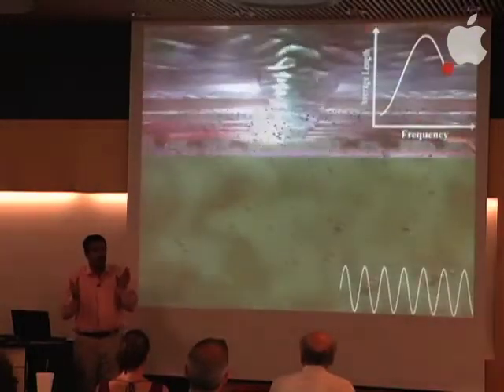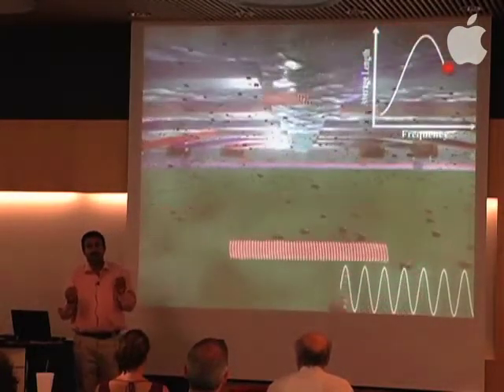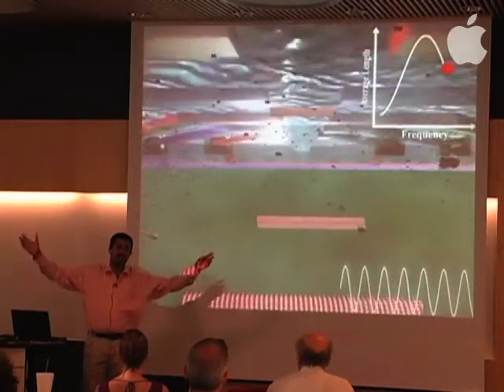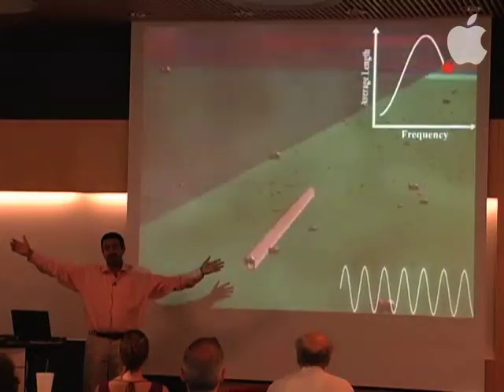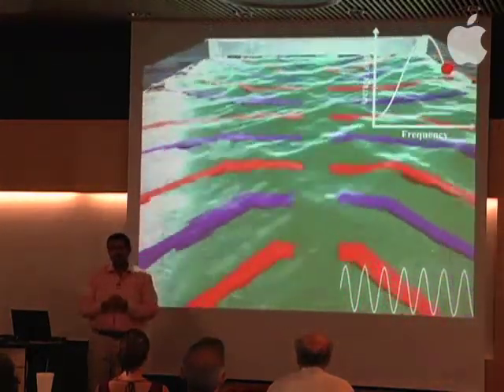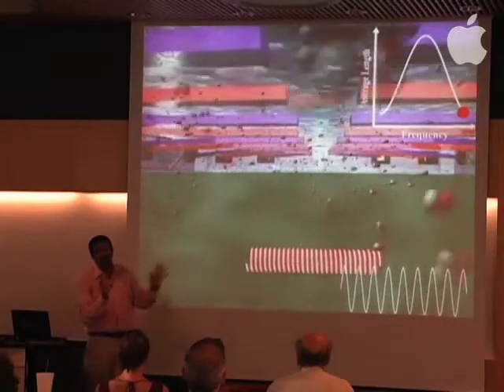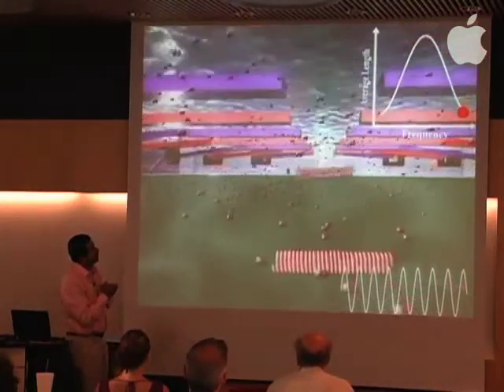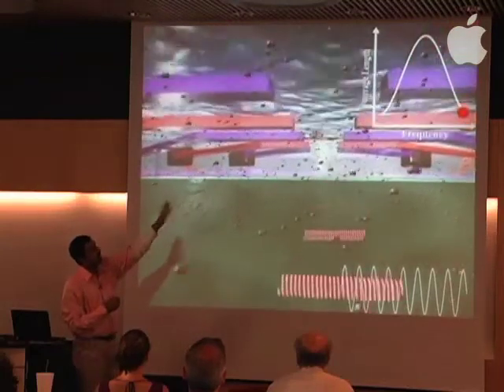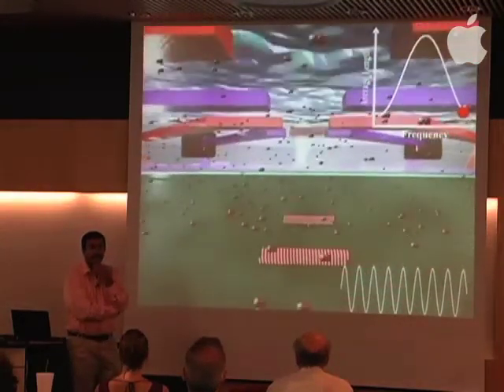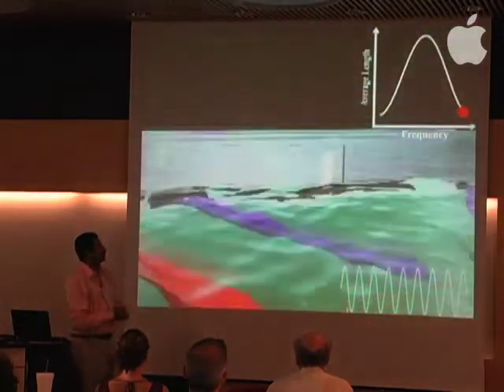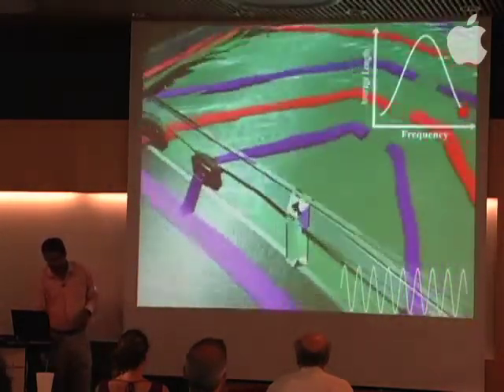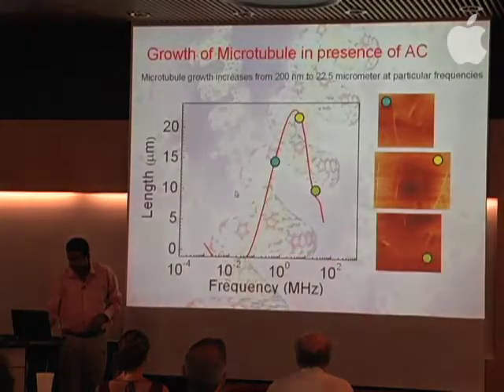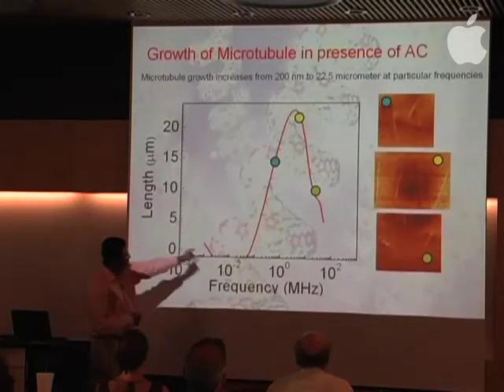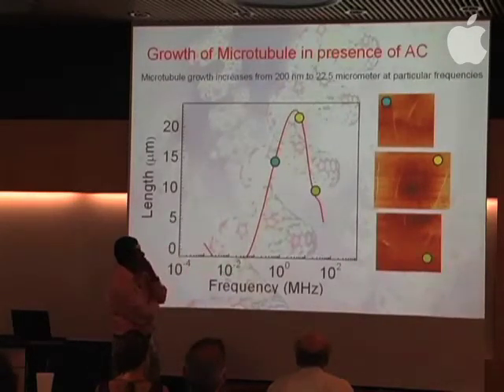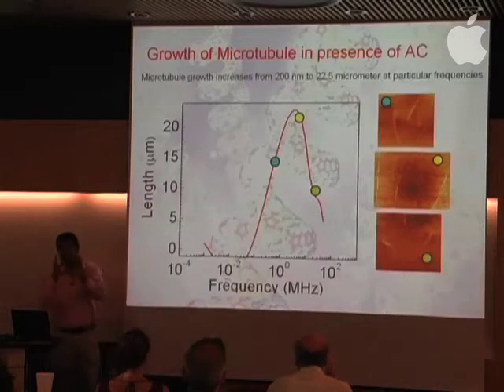But if you go towards 3.77 megahertz or around that signal, you will find that within 2 or 3 seconds, giant microtubules, say 22.5 micrometers long, are created and fall all over the surface. So it's a beautiful experiment, I believe, a very simple and beautiful experiment, to realize that something is definitely happening near that frequency range, which is enabling the entire system to grow and create large architecture. So this is the experimental result. If you go at a particular frequency, you'll find long ones. And those are some of the images of the surface.